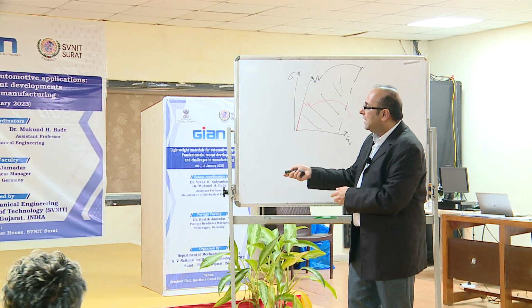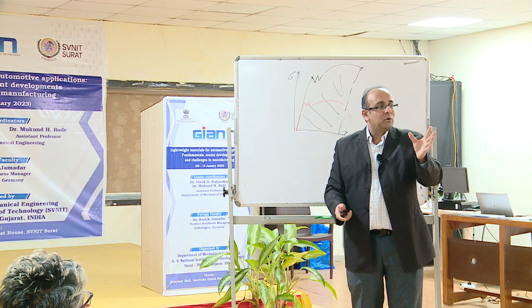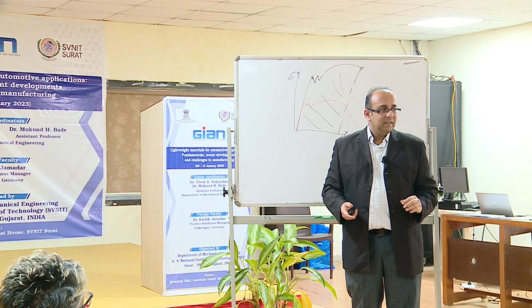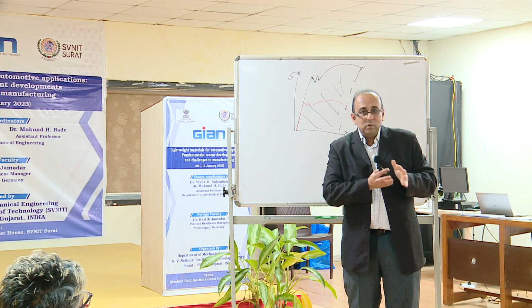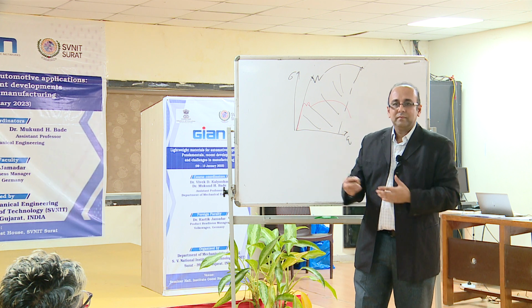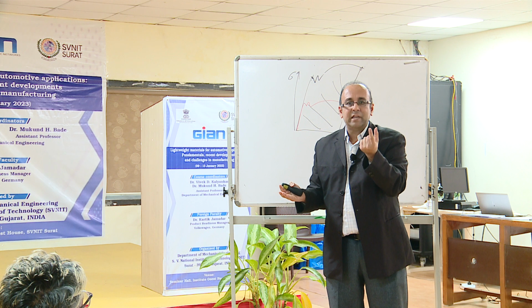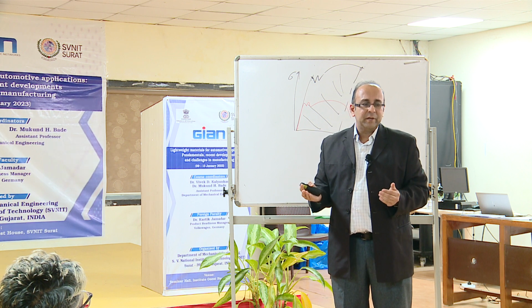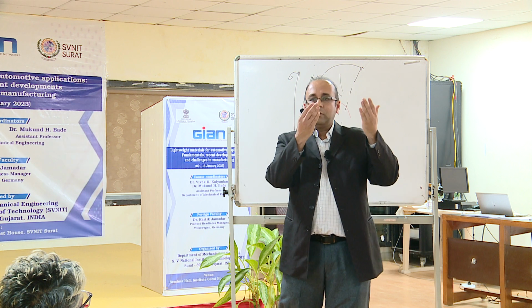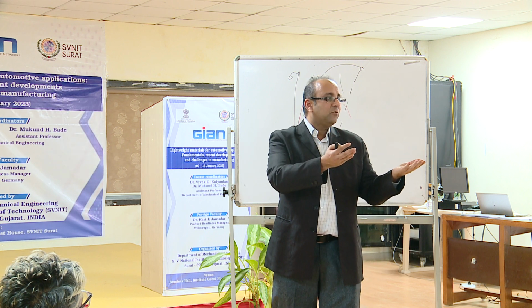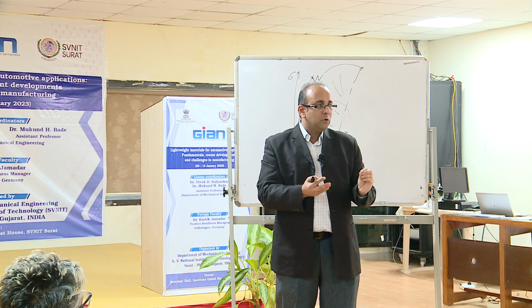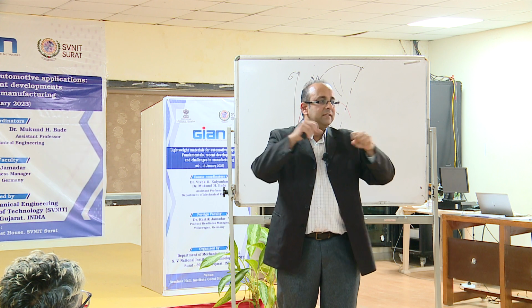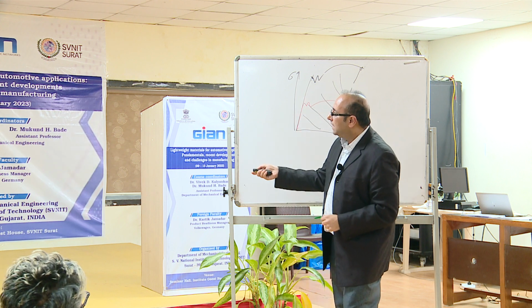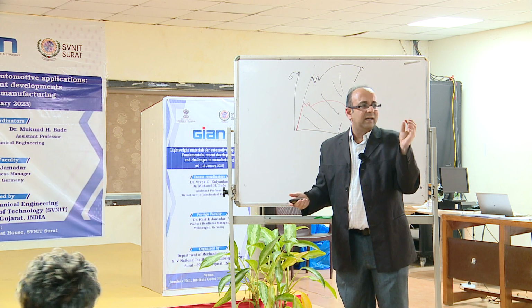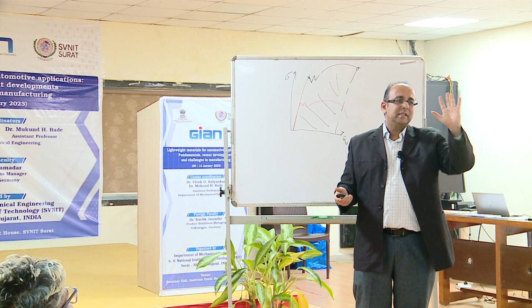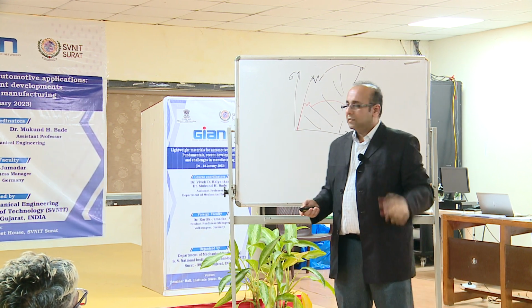Then came the bake hardening steel, as I told you, putting nitrogen first, carbon, mainly nitrogen. And they realized that this nitrogen basically goes inside the crystal structure when you give the temperature. That's how the word bake hardening. So the first hardened steel which came into the picture was bake hardened steel. And when do you give temperature? You deform the part, you send it for the painting, and there is a temperature of 180 degrees centigrade, and that is sufficient for the nitrogen to move inside the crystals. And that's how the strength is created. So the second one, bake hardening steel, you get around a little bit more, 300 megapascal of yield strength. A little bit more we got, that's it.